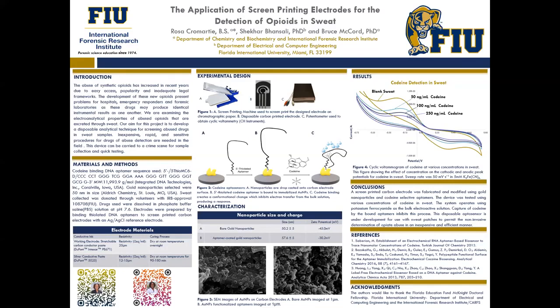So in figure 4, we can see the cyclic voltammogram of various concentrations of codeine. It shows that there's a signal drop when codeine increases. So the more codeine that is present, it blocks the reaction binding of ferrocyanide, which means that the binding of codeine interferes with the ability of ferrocyanide to access the aptamer bound to gold and for the electron charge transfer. So this voltammogram correlates to what we see in the zeta potential and the size, as well as in the schematic design that's being shown.